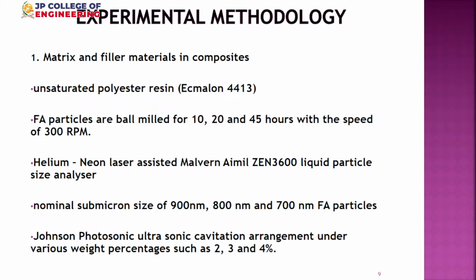We checked the role of particle size, and we also selected 3 different weight percentage additions: 2, 3, 4. These are based on our previous literature review. You have to identify some range, from which you can go for further fine tuning to find the most suitable one. That's the study purpose. The broad range obtained from literature showed that anything more than 5% is not suitable, and anything less than 1% will not give the expected property. Therefore, we selected 3 ranges: 2, 3, 4. The particle size could go further, but our limitation is we could not go below some 500 nanometer, as the machines we have could not give very low particle size. So accordingly, we selected the particle size and the particle percentage, and it has been made. Next slide, please.